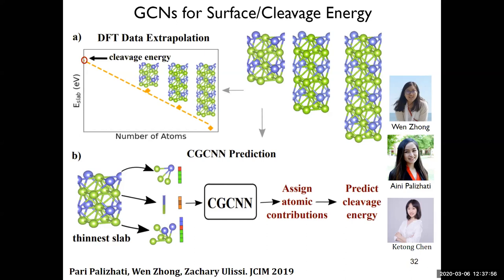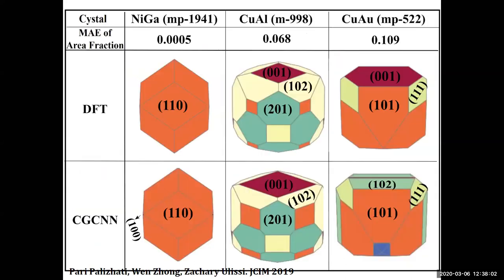If I take those cleavage energies and blindly assume that they are surface energies and put them into this little nanoparticle construction tool, these are three different crystal structures that I had cared about for different chemistries in the past. DFT says this nickel gallium is all 110, and the machine learning model agrees. That one is easy, that one's actually symmetric. Copper aluminum, qualitatively, we're close. Copper gold, we're pretty close. There's just an additional facet here.